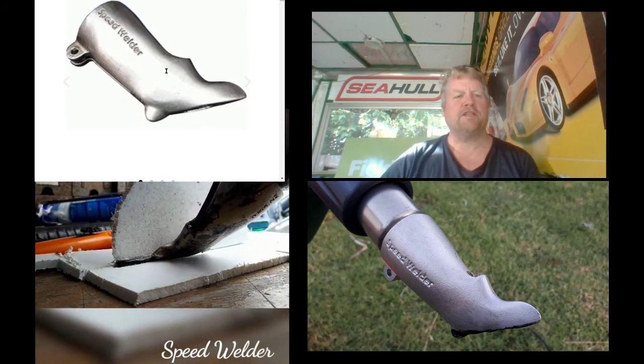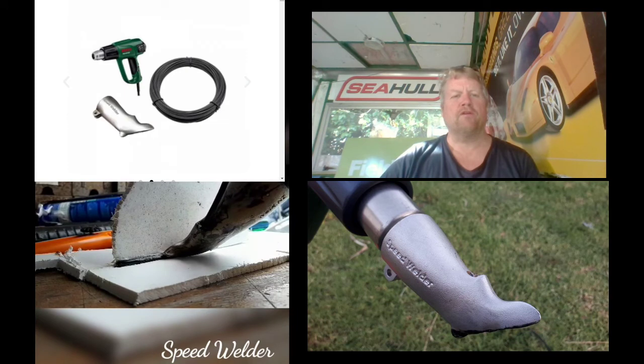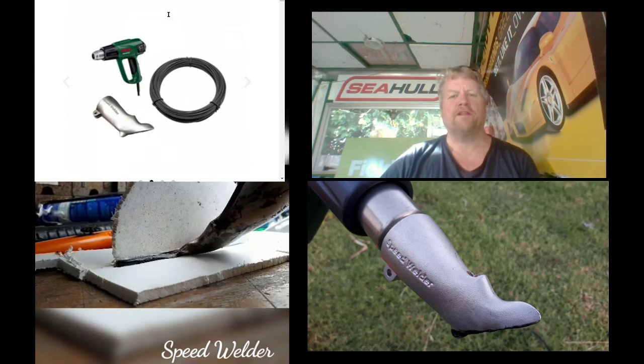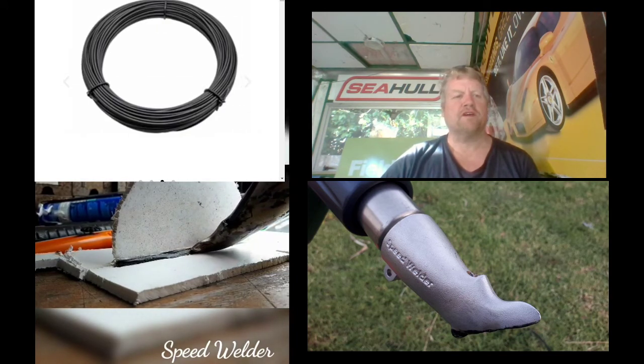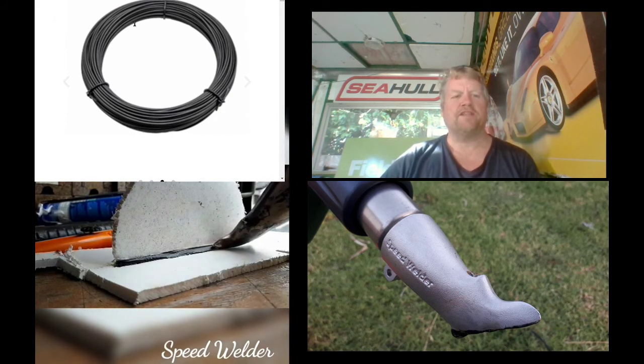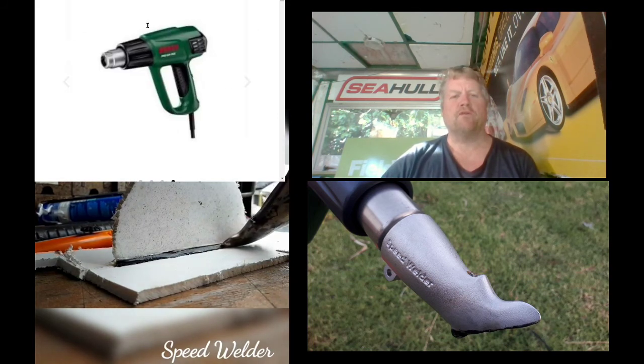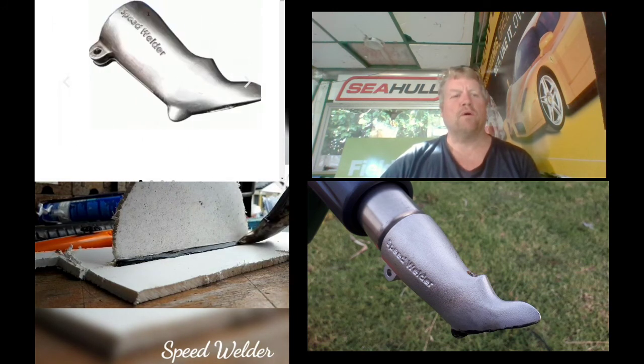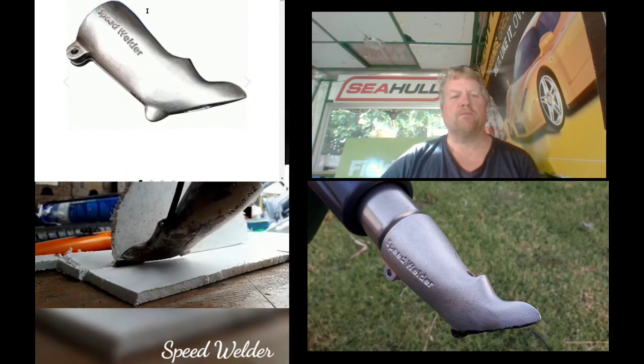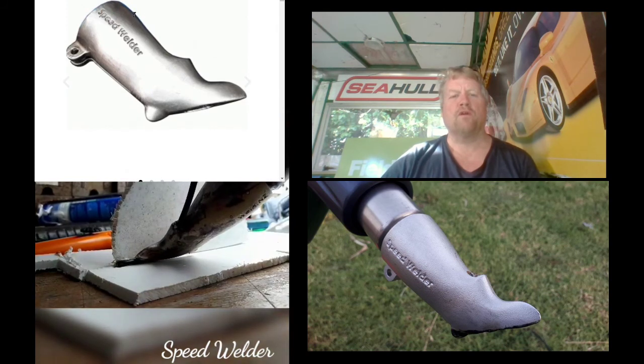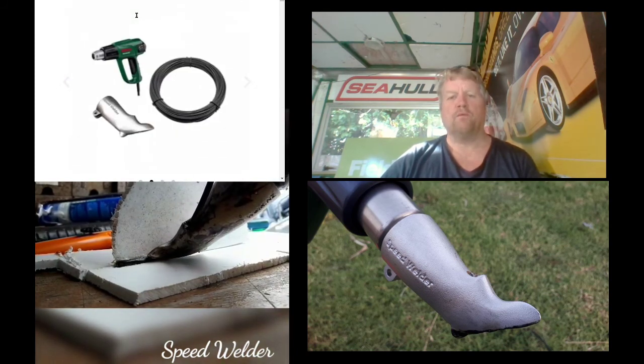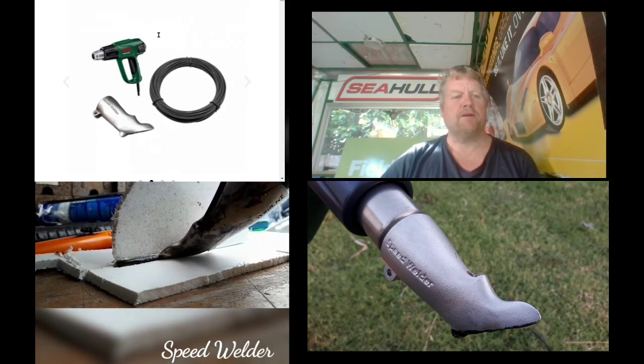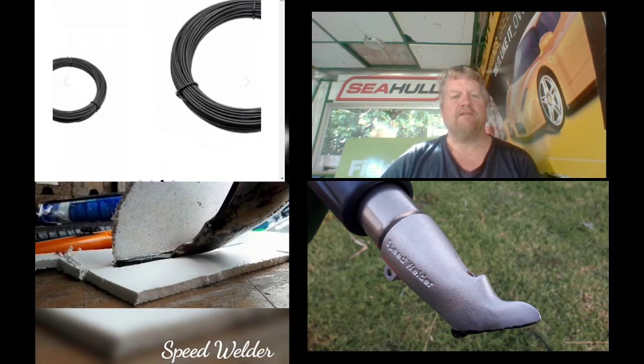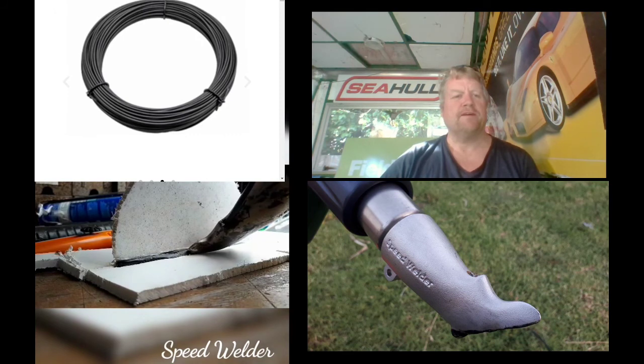Once up to temperature, simply insert the welding rod into the speed welding nozzle and apply a downward pressure on the welding rod itself. Apply approximately 2.5 to 3 kgs of downward pressure, forcing the welding rod through the speed welding nozzle and into the welding area. The welding tool will only need to be supported, as the force of the welding rod will move the tool along in the weld area with ease. The speed welding process is fast and very easy to achieve.